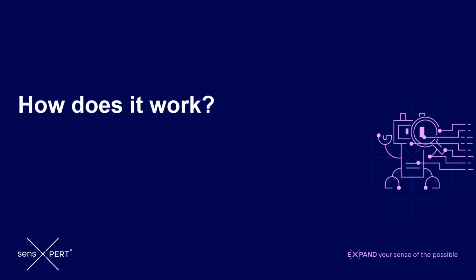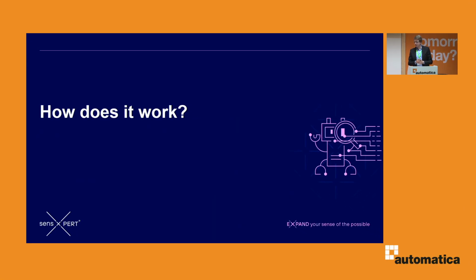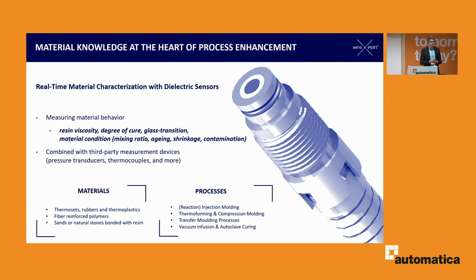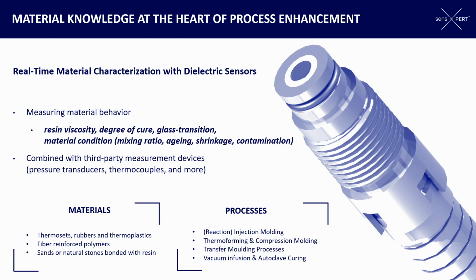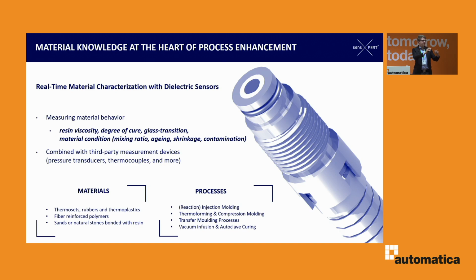So let's look a little bit more into detail regarding how this works. The sensors we use, as I mentioned before, are dielectric. So this means we basically have a little capacitor, and the material, the plastic, is going to act as a dielectric. And we apply an alternating voltage, and the material is going to react, because in the plastic you have macromolecules that have charge carriers, dipoles that can orient within the electric field. And this is something that we can then detect and conclude how easy it is for the molecules to move, essentially.